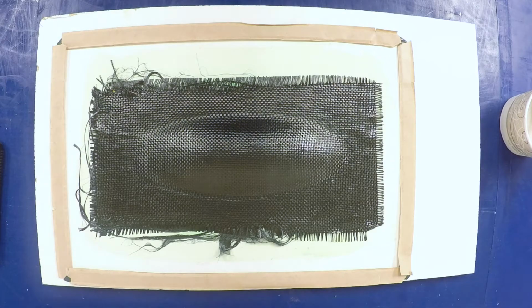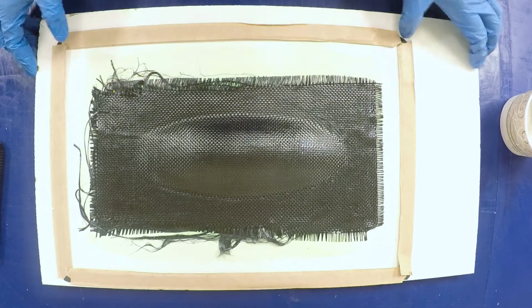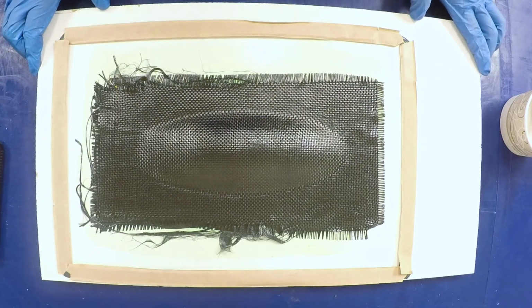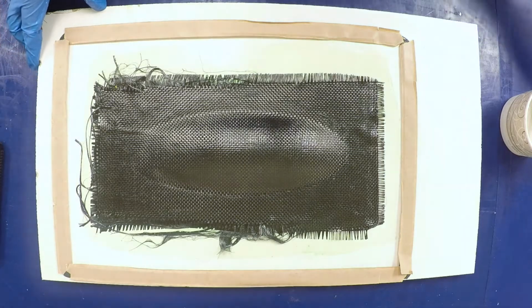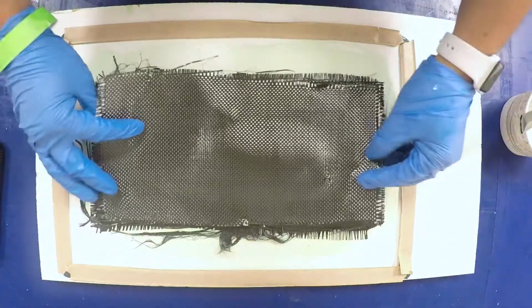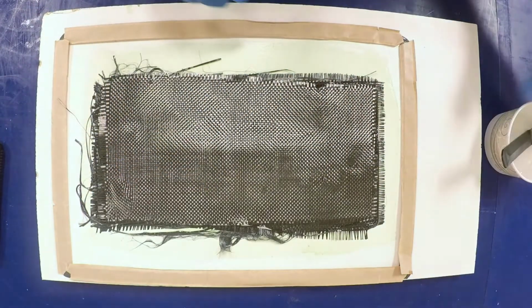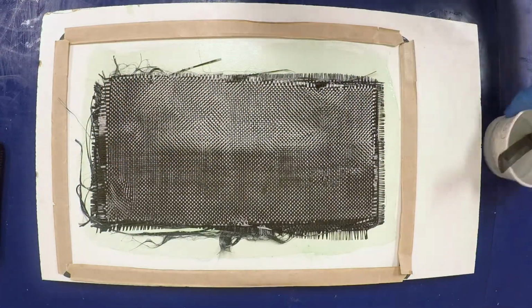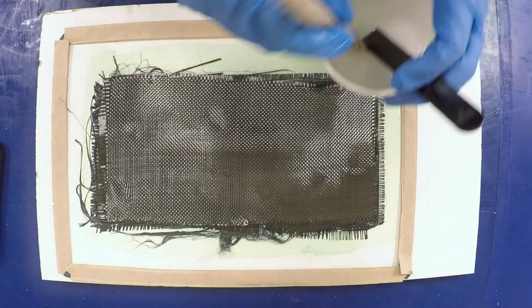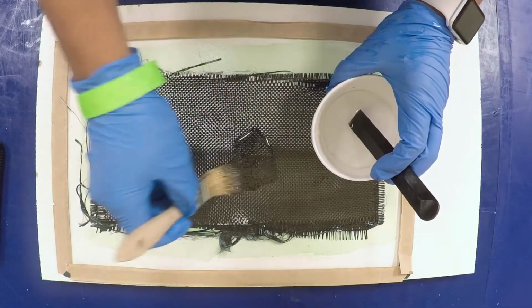For this procedure, you can follow the same steps as when creating an atmospheric pressure layup. However, due to the vacuum bagging, you also have the convenience of wetting the fibers directly on the mold by dabbing epoxy with a paintbrush to tack the fabric to the mold. Due to the vacuum bagging, the pressure exerted on the part will remove any excess epoxy away from the fiber and prevent it from staying in the final product.